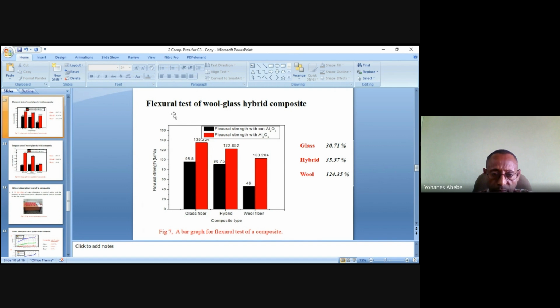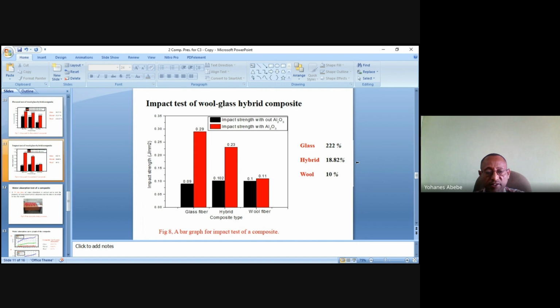The same holds true when we see the flexural test of the wool glass hybrid composite, the glass fiber, the hybrid, and the wool fiber. The percentage improvement in the flexural strength of the composite, that of the glass fiber composite is 30%, and for the wool composite is 120%, and that of the hybrid is 35% improvement obtained from these tests.